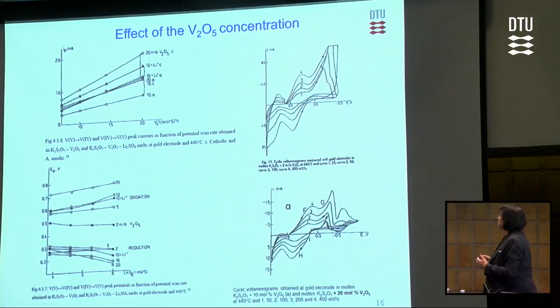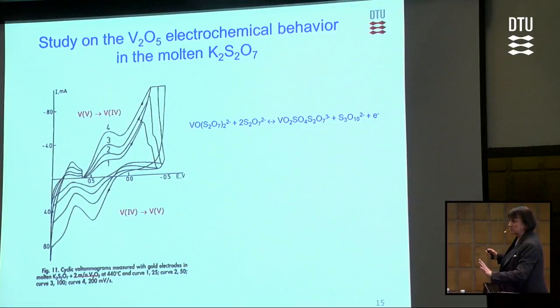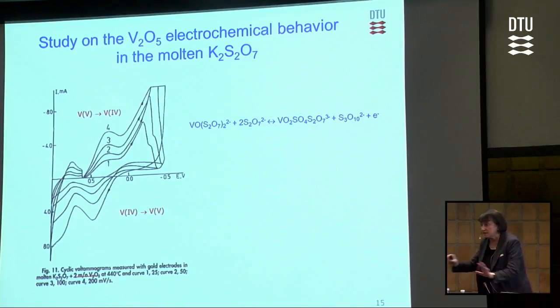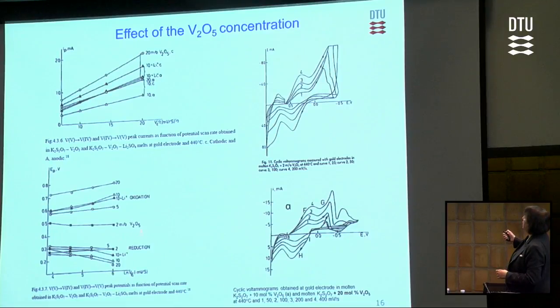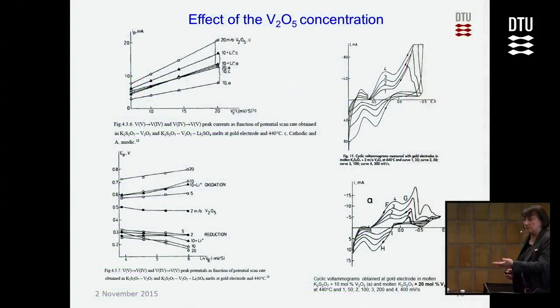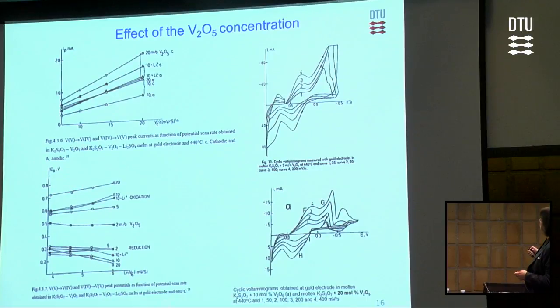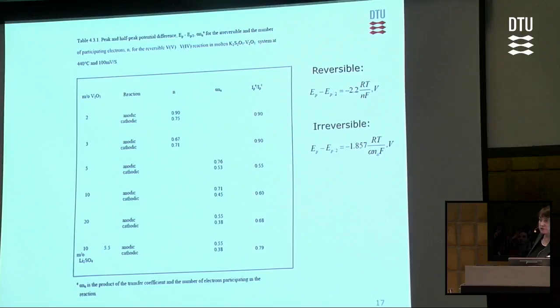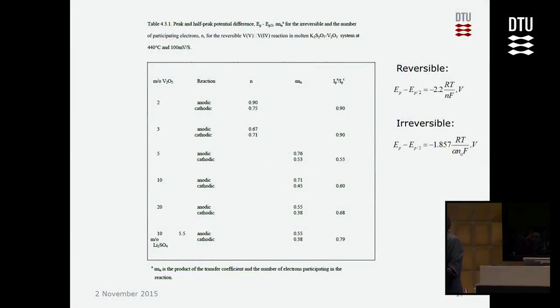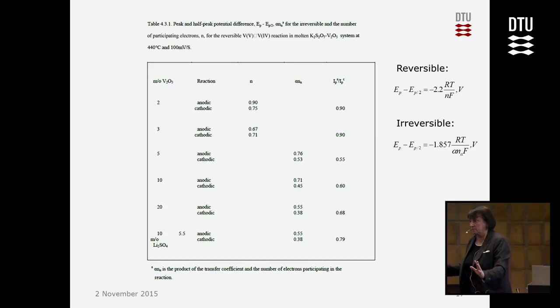So if we want the catalyst to work well, we need this ideally reversible. Because that will be the rate determining step, if they are reversible and fast, that's it, the catalyst is okay. So when we go up to 20 mol%, the reaction becomes classically irreversible. So the slowest step is electron transfer. And the best sign of this is a linear dependence of peak potential on the logarithm of potential scan rate. So you can just compare this, and you will see the difference. Okay? I calculated, using these equations, the number of electrons participating in the reaction depending on concentration, and it was 1. It was monomeric vanadium.